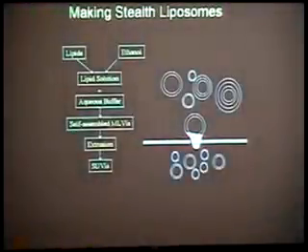Okay, so with that introduction to liposomes, this is how you make them. You self-assemble lipids in aqueous medium. You extrude them through these polycarbonate filters. These are nucleopore filters which have cylindrical pores, so they're not your typical depth filter configuration, but they have cylindrical pores, and they essentially act as extrusion dies, and you can make a fairly tight distribution of sizes.